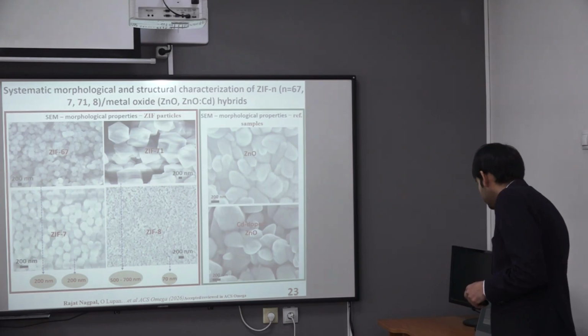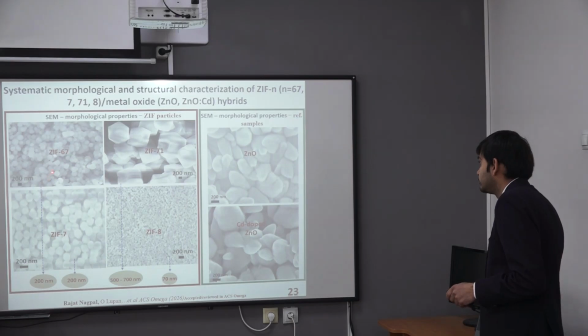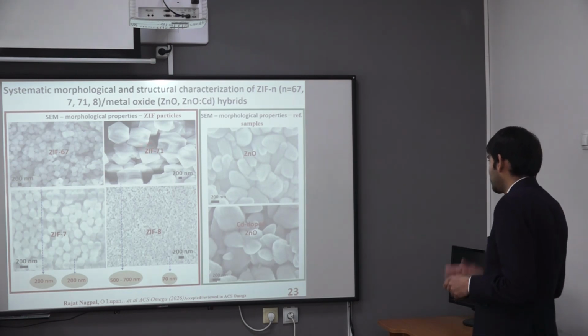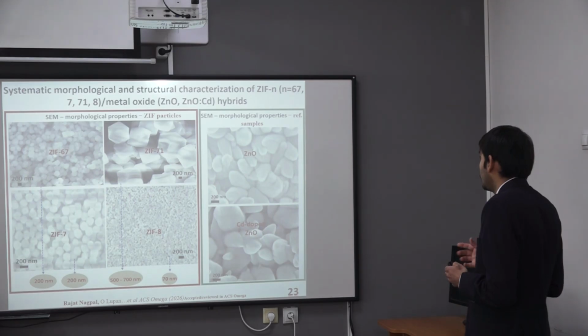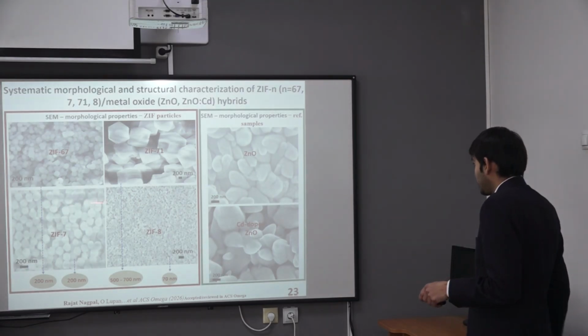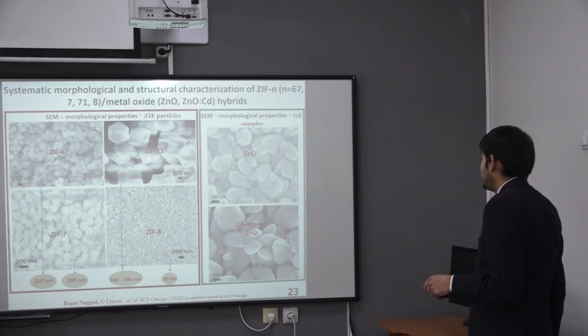Yeah, one can see, for example, on the left panel, the upper right, the ZIF-71, there are some lines going from left to right through the image. This could be attributed to the charging effect. Here you can see it was showing too much charging effect, and we tried to make measurements multiple times, but we were unable to get very clean images like other ZIF particles. It is maybe due to the charging effect.